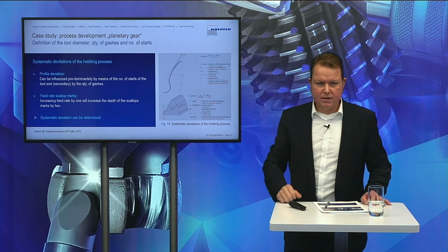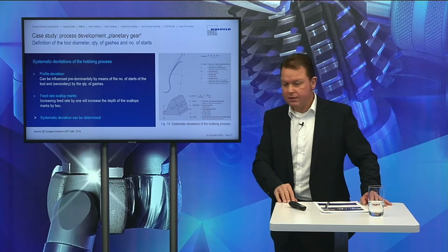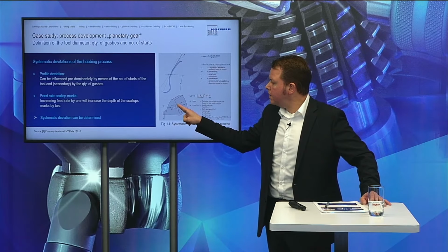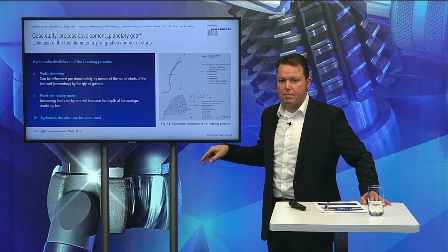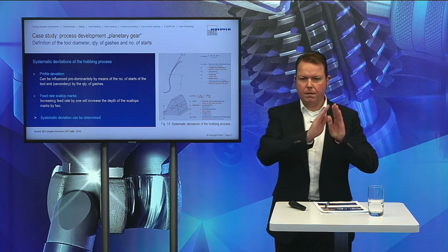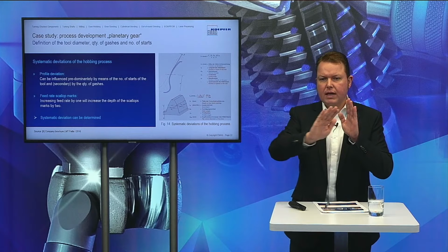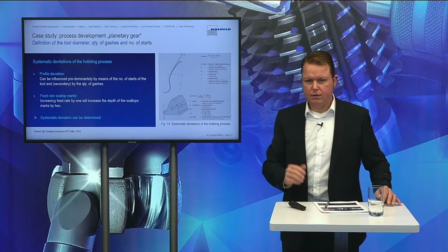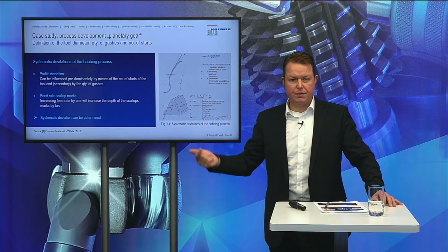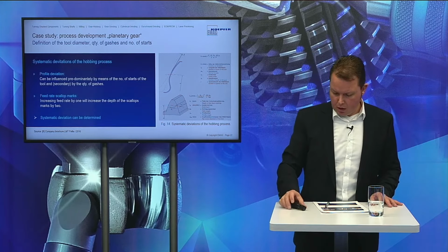The second systematic deviation is the feed rate. The feed rate will leave, in function of the diameter of the hob, traces on the lead in axial direction. And we can also determine those. They depend on the feed rate predominantly, but also on the hob diameter.